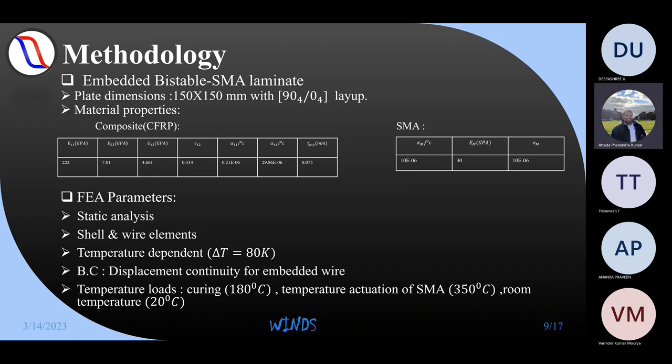But there are two things here. One is the material compatibility. The other is also the geometry involved, because you're putting a wire between the layers, which could be a source of delamination initiation and things like that. So you have to explore from both aspects. And the coefficient of thermal expansion is different between both, so I'm sure it's not easy to get continuity between the wire and the laminate.